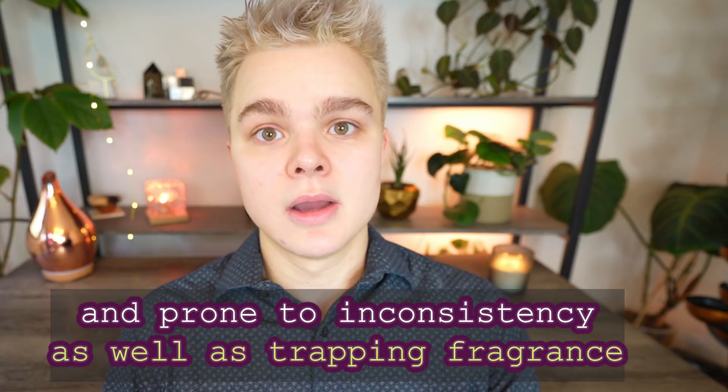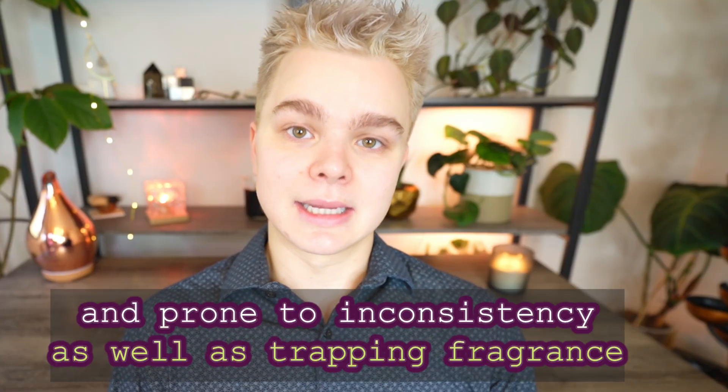It doesn't have those other features that we really don't like with soy waxes. That was kind of long-winded, but if you did enjoy this one, give it a thumbs up and leave me a comment below. This is a very, very common topic — I get so many questions on what people are doing wrong in their candle making. It's usually nothing you're doing wrong, but you can oftentimes pour at a cooler temperature to mitigate some of this initially. After you burn the candle and it reheats and re-solidifies again, the polymorphic nature of soy wax when it's on its own is just going to be prone to bumpy, frosted tops — what's really called irregular crystalline latticing.